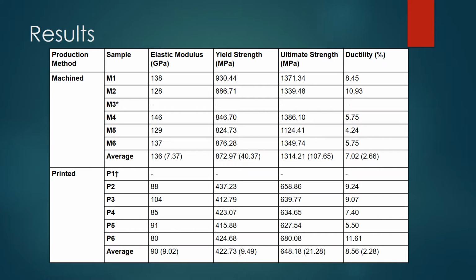But for the rest of the samples, we have summarized here the elastic modulus, yield strength, ultimate strength, and ductility, as well as the averages for the samples. On average, the machine samples had a higher elastic modulus, yield strength, and ultimate strength, but a lower ductility. Especially when you look at the ultimate strength, you can see that there's quite a big difference, where the machine samples on average had an ultimate strength of 1314.21 megapascals in comparison to the printed samples, which on average had an ultimate strength of 648 megapascals.